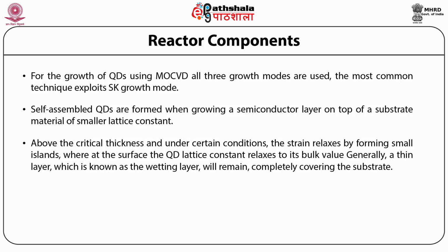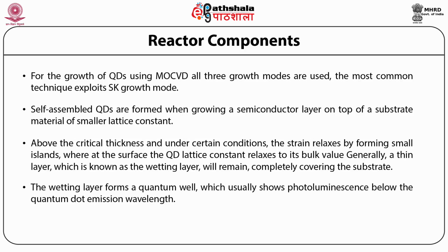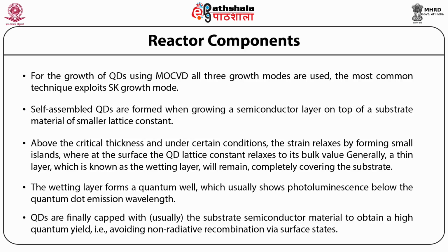Generally, a thin layer which is known as the wetting layer will remain completely covering the substrate. The wetting layer forms a quantum well which usually shows photoluminescence below the quantum dot emission wavelength. Quantum dots are finally capped with the substrate semiconductor material to obtain a high quantum yield, that is, avoiding non-radiative